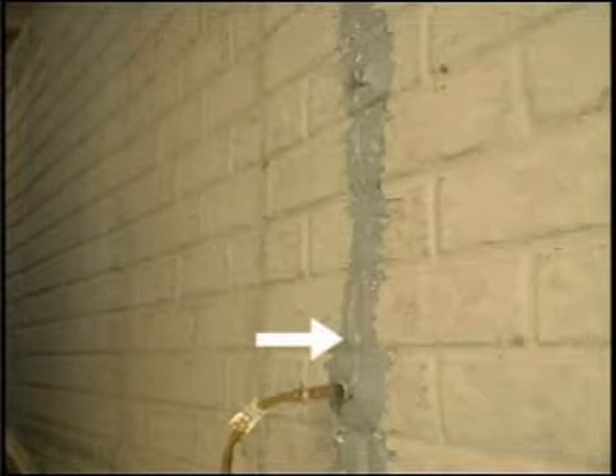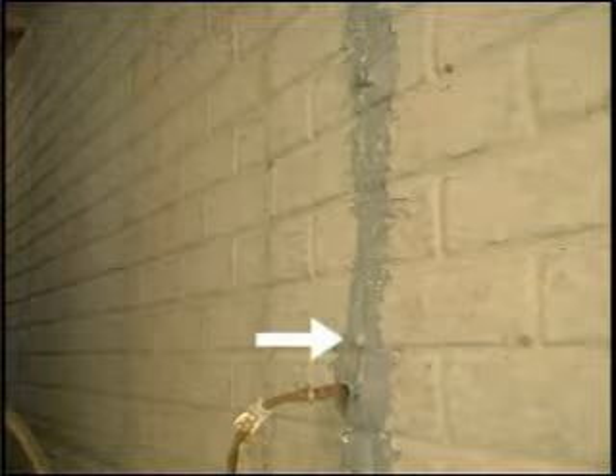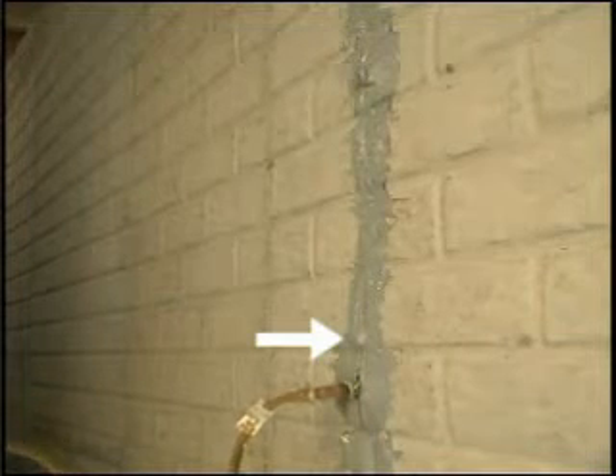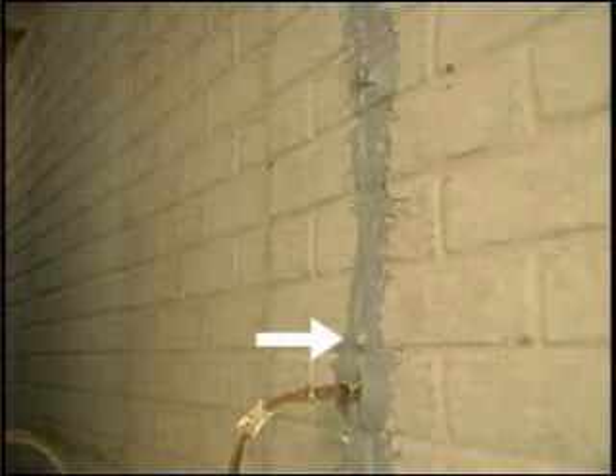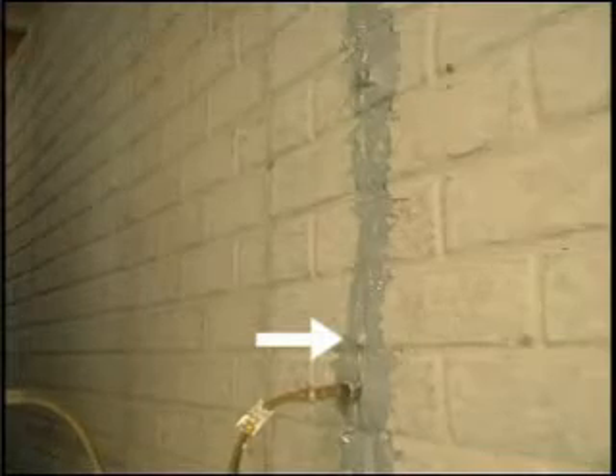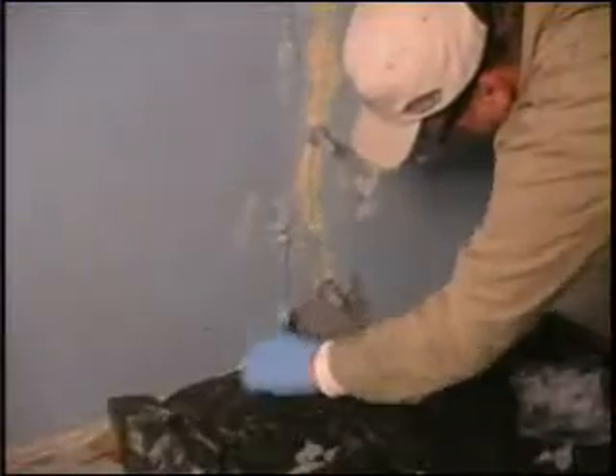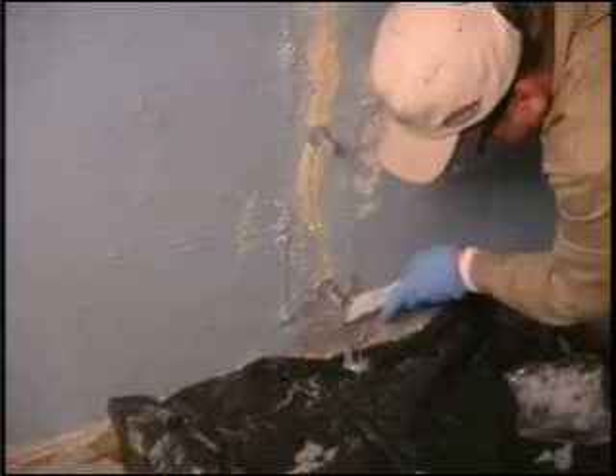These are small leaks that may appear if 1. The surface seal has not set up completely, or 2. There are small pinholes in the surface seal application. This will not affect a successful outcome, but should be minimized by careful application of the sealer.